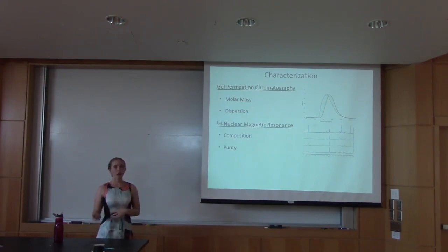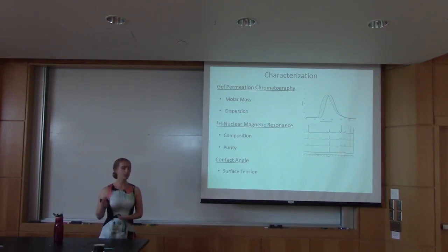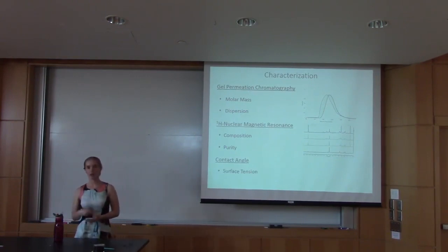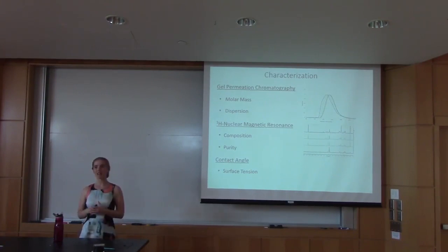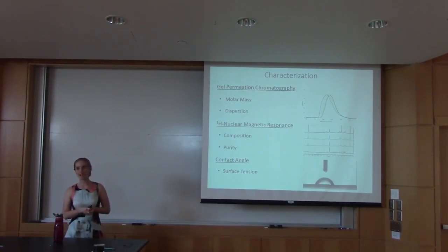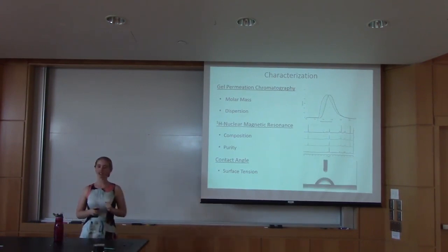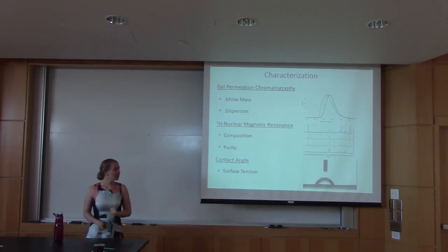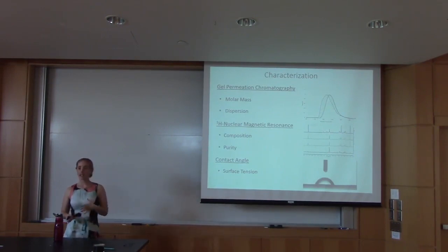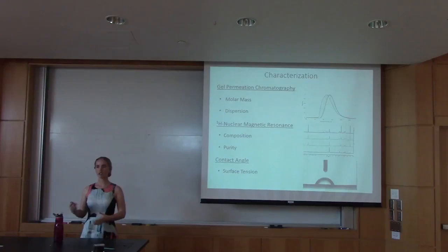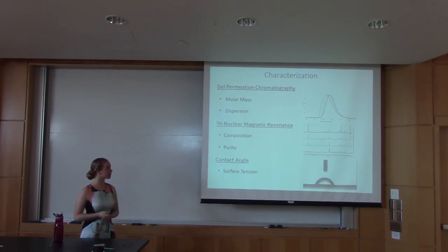Where we really tell how hydrophobic or hydrophilic this surface is is through contact angle measurements, which tell us about the surface tension, which then tells us how hydrophobic or hydrophilic the surface is. And this data is a little bit more fun, a little less traditional in the fact that it's not a graph that you get out. Instead, you get this nice picture, and that's a water droplet on our surface. So with that, I'm going to go a little bit into contact angle and how we used it, how it becomes quantitative, because right now we just have a picture and it looks nice, but we don't have any quantitative data.